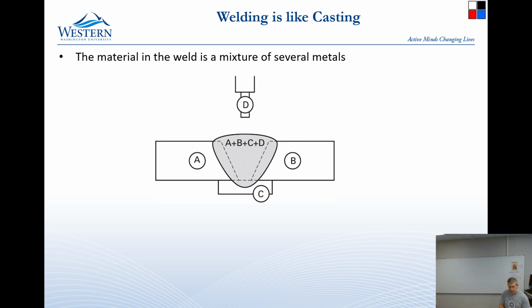The one place where we undermatch things is when we have really brittle materials. If A and B in this are really brittle materials, if we overmatched the weld and then it shrinks, it's going to put incredible tension on the two pieces of base material. And if they're brittle, it will just break loose from the base material. So when we have really brittle materials, we undermatch, and as the weld cools, it will stretch to fill that rather than breaking the two pieces of material on the sides.